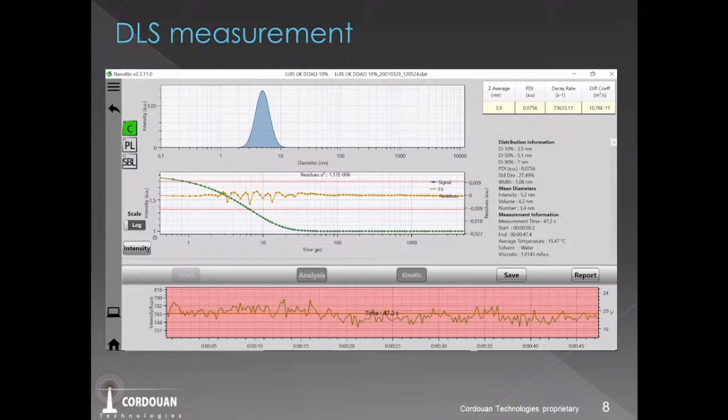So the idea, when you use a mathematical algorithm, you need to look if the mathematics have done a good job. For that, we are doing the difference between the theoretical data, which is the green line, and the experimental data, the experimental dots, which are the blue dots, okay? The yellow line here, what we call the residues, is the difference between the experimental data and the theoretical data. When you find that the residues are below 1% error, you can assume that, okay, mathematics is working well. You have reasonable results, and you can expect that the level is really good.